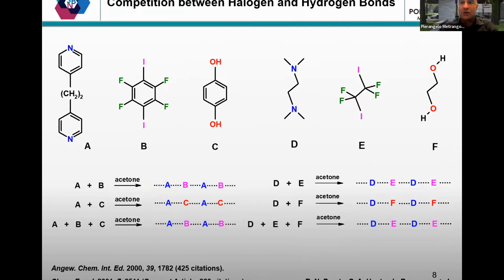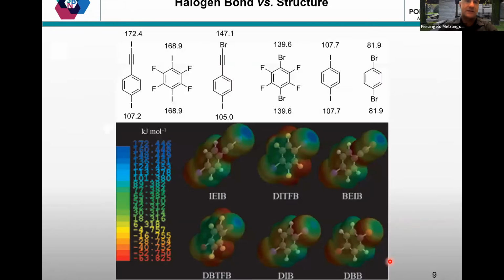And also in 2017, Lee Brammer, Robin Perutz, and Chris Hunter made the same experiments, and luckily they got the same results. But not only fluorinated compounds can behave as halogen bond donors, because even without fluorine, iodine, when polarized by triple bonds, for example, is a very strong halogen bond donor. But even diiodobenzene, which is a very common molecule in organic chemistry, has an iodine halogen bond donor.